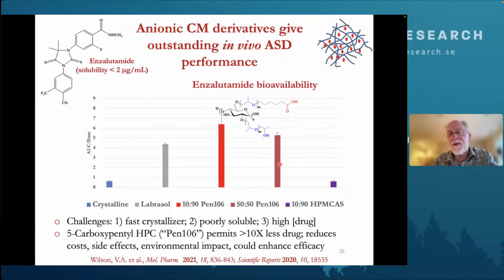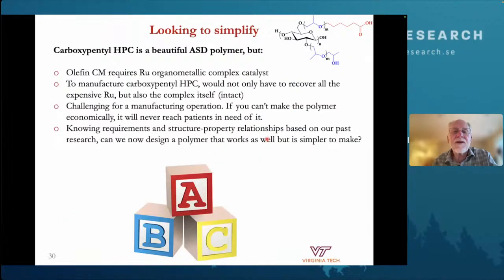Here's a formulation with that same polymer, our polymer, but now at a 1-to-1 ratio, polymer to drug. And it's not quite as good as the 1-to-9 ratio, but almost, and it's significantly better than the commercial formulation. So we've solved both the problem of fast crystallization and the problem of low potency drug at the same time. Really a promising derivative. So it's a great polymer, it's a great ASD polymer. Like I said, it's the best one I've seen, but it's got a problem.